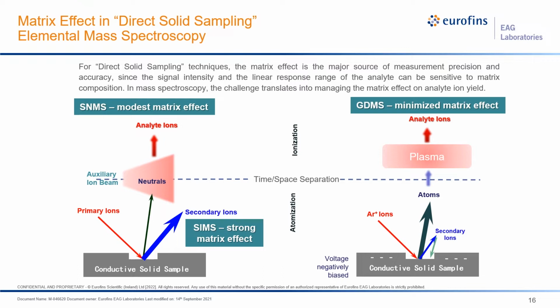Now, what if we suppress the secondary ion yield and boost the neutral yield? We have GDMS here. This is a typical example of how the matrix effect is minimized. It has a nearly complete atomization and ionization separation, so the analyte atom signals are infinitely diluted in the plasma before they are analyzed. From the analyzer's point of view, it only sees the analyte atoms in the plasma and the chemistry memory of the matrix is completely gone. So this allows GDMS to do quantification even when strict matrix matching standards are not available.